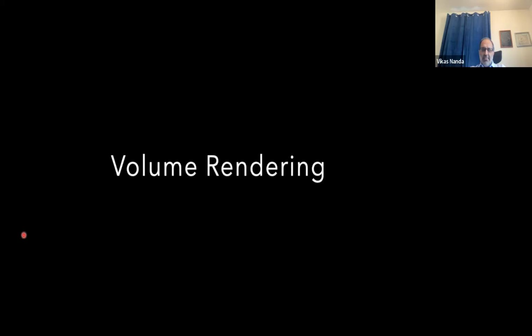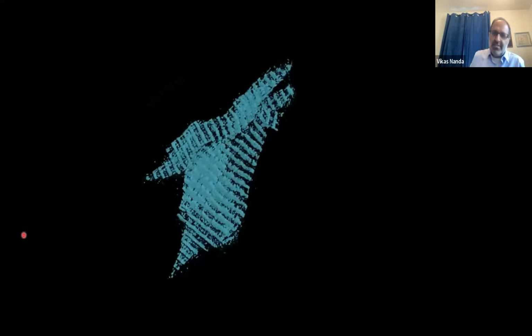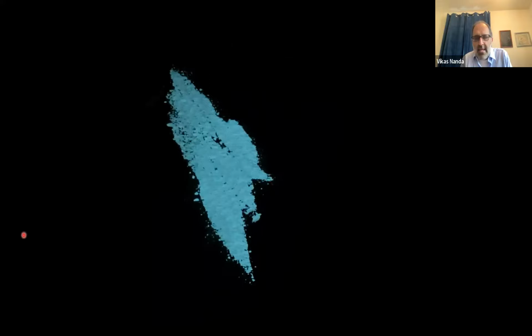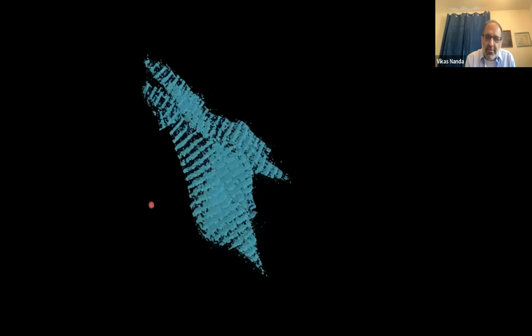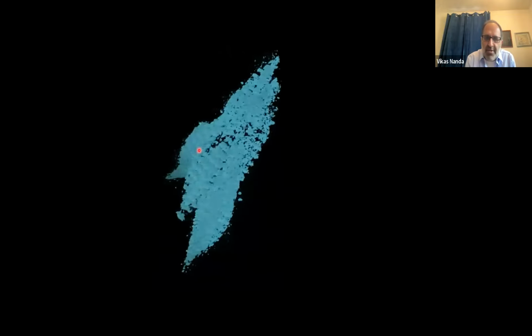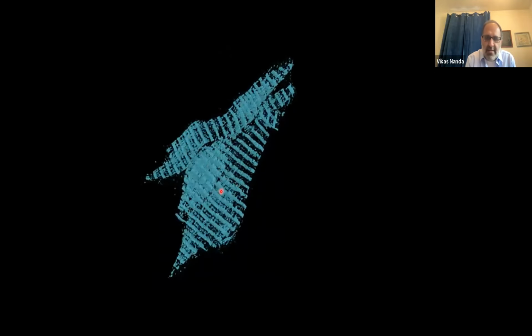And then we can use those images to do a volume rendering. And so this is the actual fiber structure here that you're looking at. And you can see the banded fiber throughout. What's also interesting is we see that with what looks like multiple fibers coming together, we get this alignment between the fibers, which suggests that once the fibers form, these surfaces still may be sticky and allows them to sort of orient relative to each other. And this is something you see with natural collagens as well.